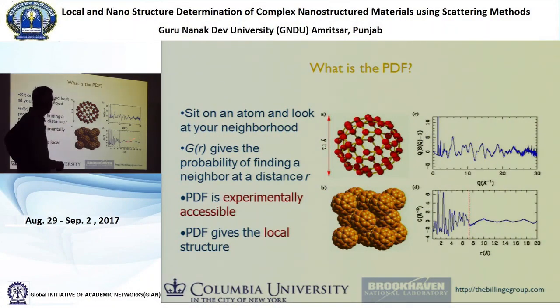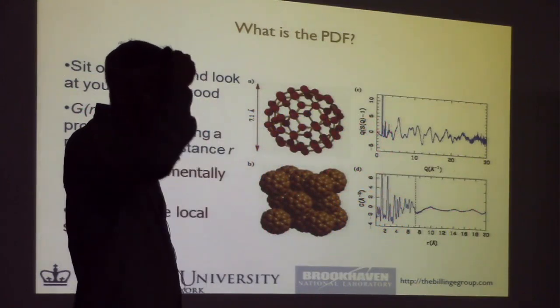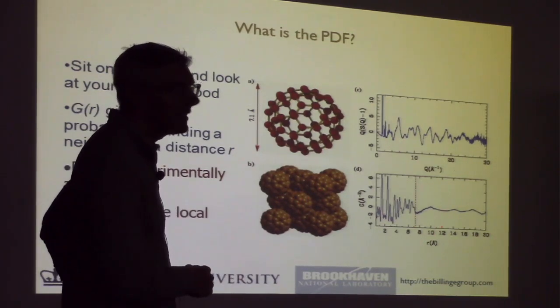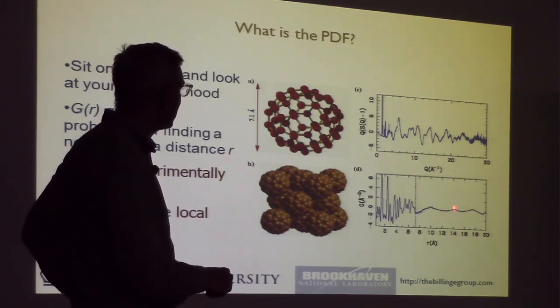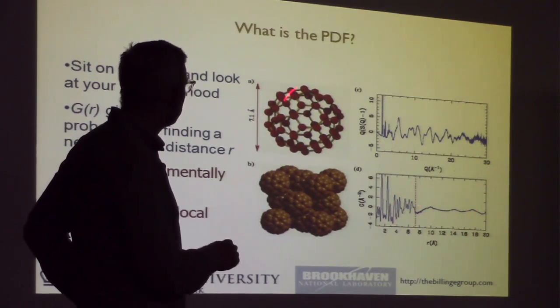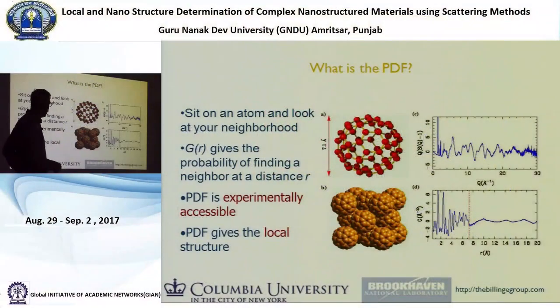And so it turns out that actually there is a little bit of structure out here. You see three peaks, and the peaks are telling you how these balls pack. So it turns out that the ball-ball separation is 10 angstroms. So there's a peak at 10. And they form an FCC, face-centered cubic arrangement. So the second neighbor distance is root 2 times 10. Third neighbor distance is root 3 times 10. Root 2 times 10 is 14 point something. Root 3 times 10 is 17 point something. So these peaks down here are telling you how the atoms are arranged in the ball, and these peaks out here are telling you how the balls are arranged.